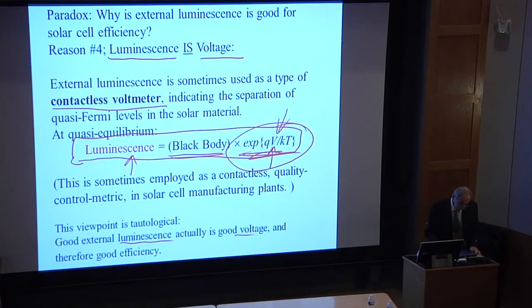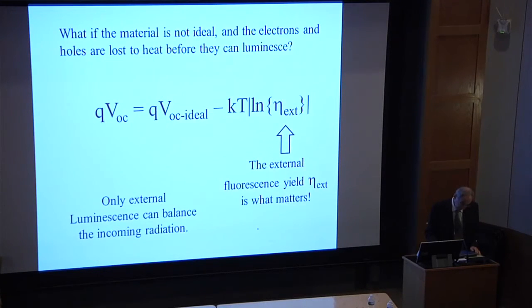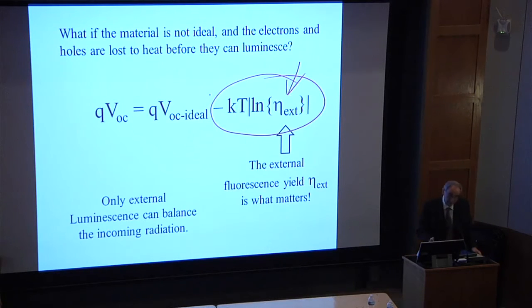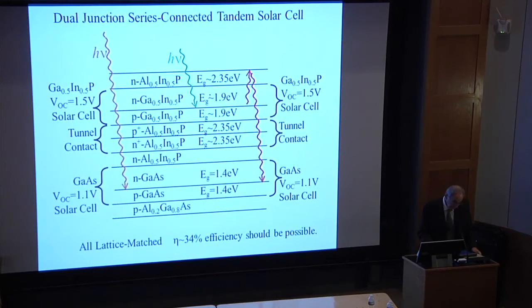But as I say, there's a bunch of other reasons, and they all amount to the same thing, that you want luminescence. And it was anticipated in Shockley's paper, except he didn't quite write it in this form, but this was applied in Shockley's paper. You lose voltage to the extent that you fail to get 100% external luminescence efficiency at open circuit. So at open circuit, the electrons and holes have no place to go, and if they go into heat, that's obviously bad. So if you get 100% of the light out, then that's good. So that's another way of explaining it. This can be made into a dual junction. Now the dual junction is with this gallium indium phosphide. It looks just the same as what I've just shown you.